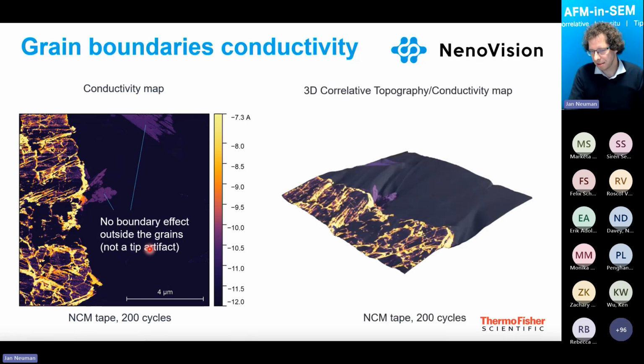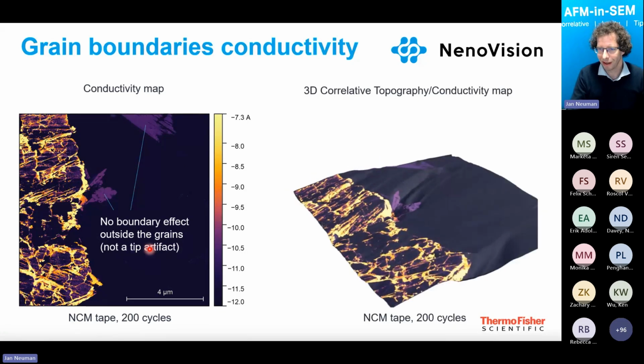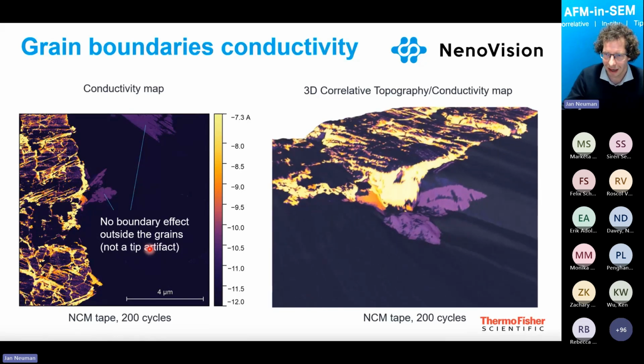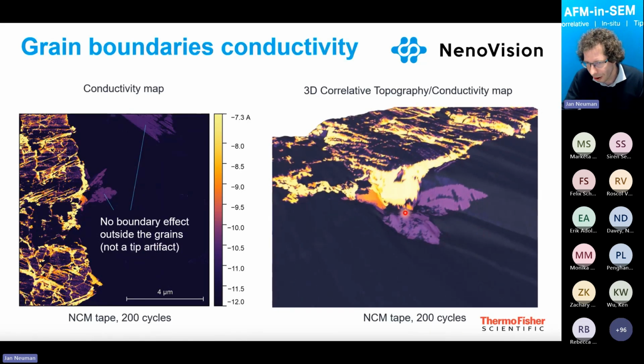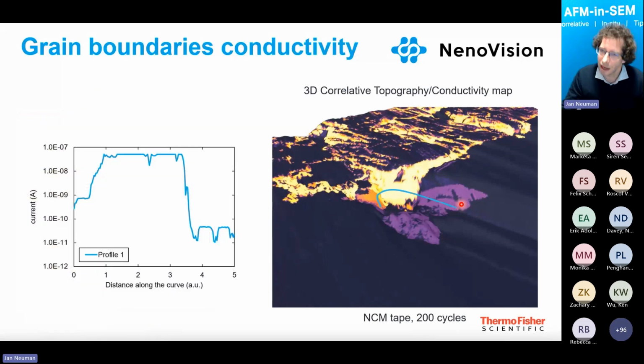For that, we utilize the benefits of correlative microscopy. So we try to dig directly inside and find the area. We have topography changes, and we also can see the different conductivity. And so we can confirm that we do not talk about an AFM artifact. These are real changes of the conductivity. Then we can make a plot within this area, and we see directly three different levels of conductivity, actually, and the conductivity changes by more than 3 orders of magnitude.